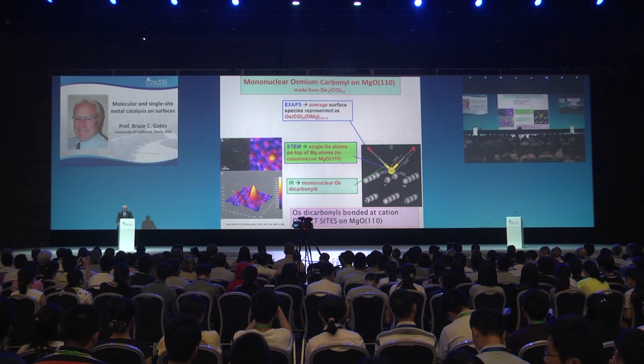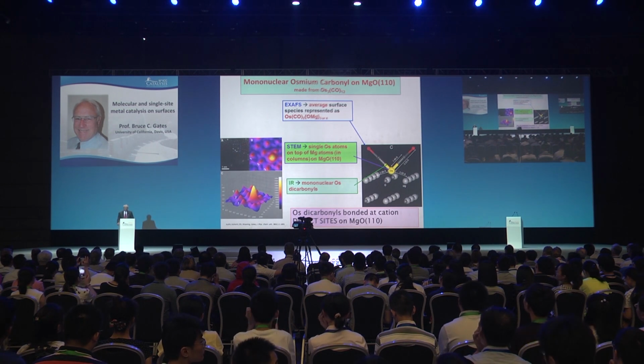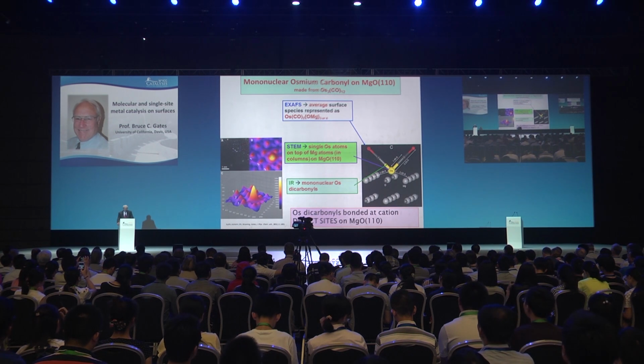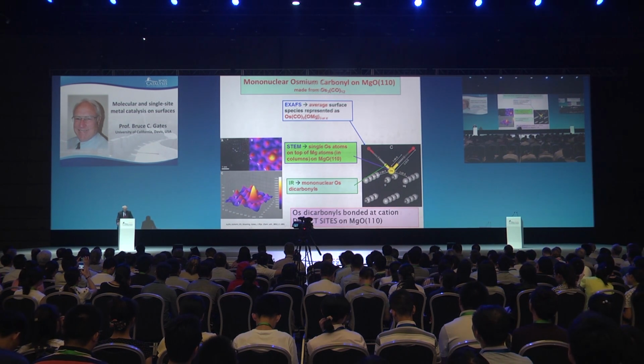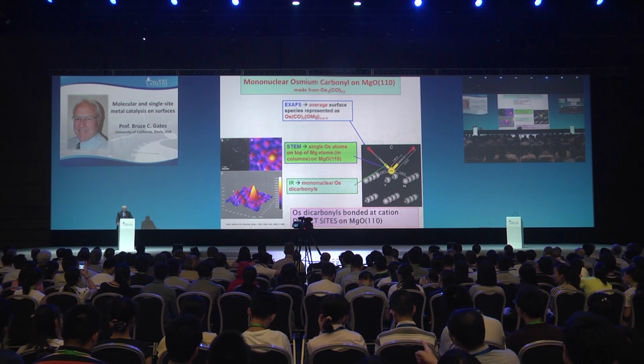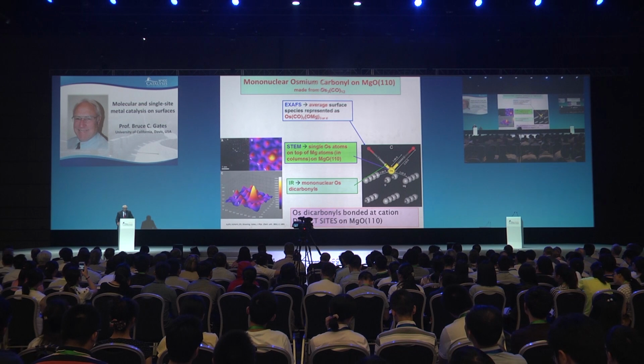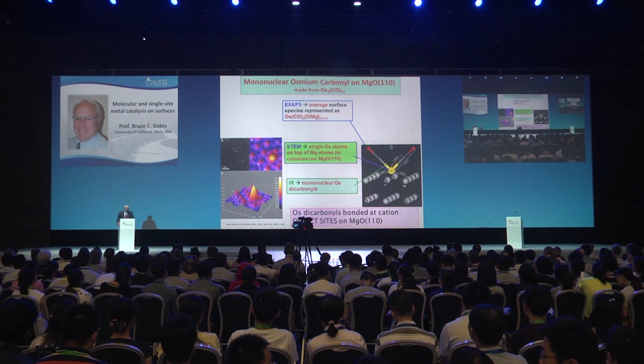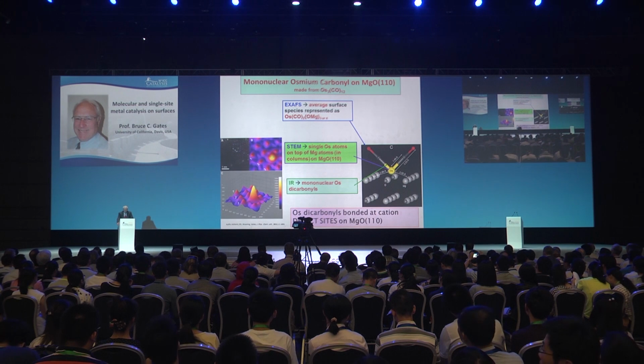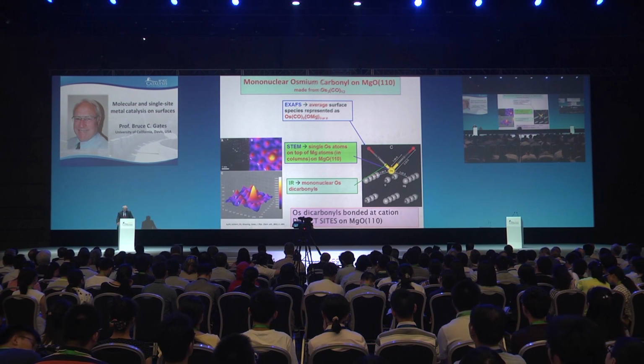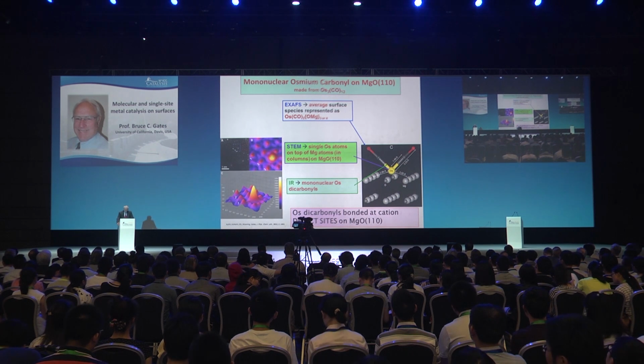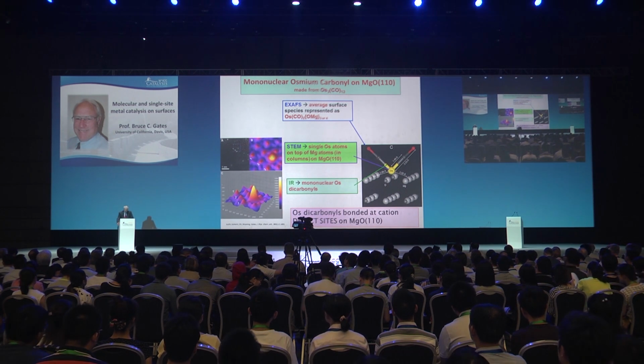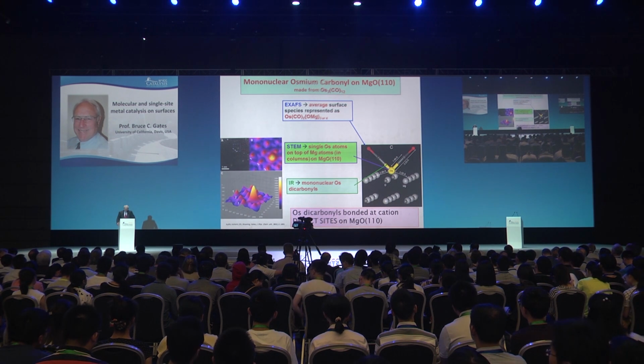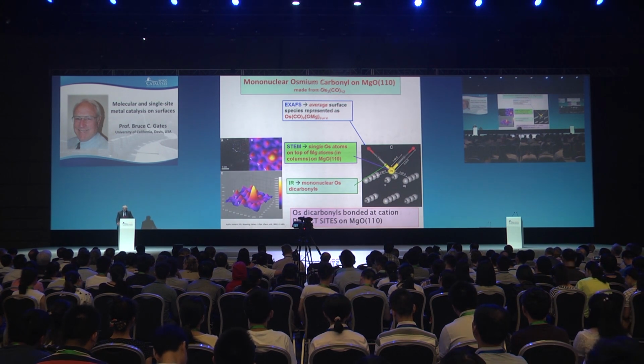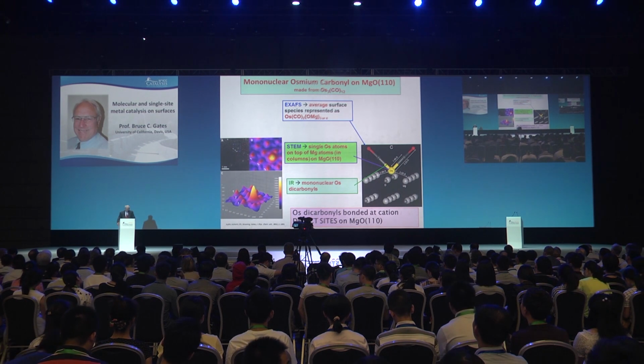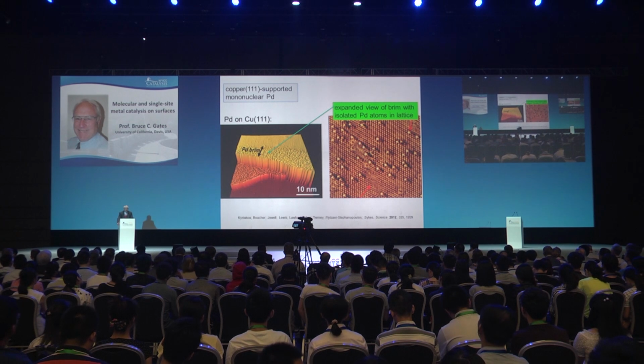So how can one understand that? Well, using structural data, EXAFS spectroscopy, which is not specific to this face but gives very similar results for metal-oxygen distances, whatever the face and whatever the metal oxide or zeolite, we can infer the metal-oxygen distances, which make very good chemical sense. They do not allow one to understand this species as present on the defect-free face of MgO(110). It only fits if the top Mg ion is missing—it's a defect site, a cation defect site. We hear a lot about that when we talk about this class of catalyst.